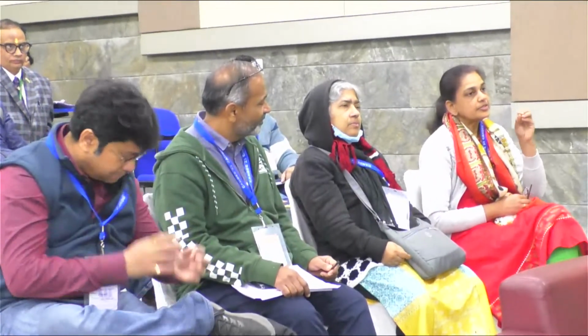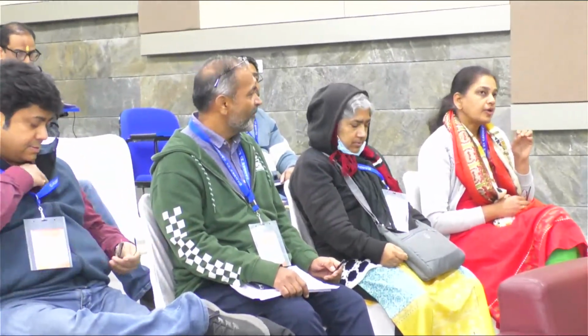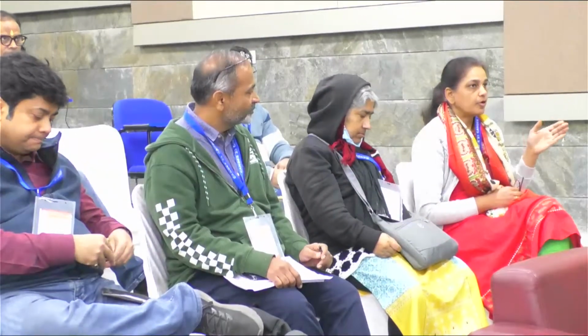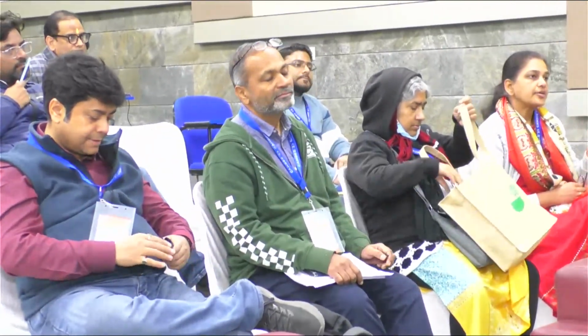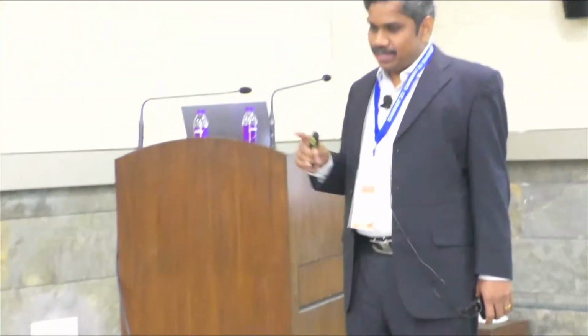This is in the experimental part. I'm thinking about this ball milling process, which we have also used. What we found is that if you go for prolonged ball milling, especially for soft materials, there is a contamination of tungsten. So, haven't you got any kind of contamination? Have you observed something? We didn't observe it because we first optimized the conditions, and then we did the milling in a high viscosity solvent like toluene, and after that we treated it at a high temperature, where the formation is more of a pure phase.